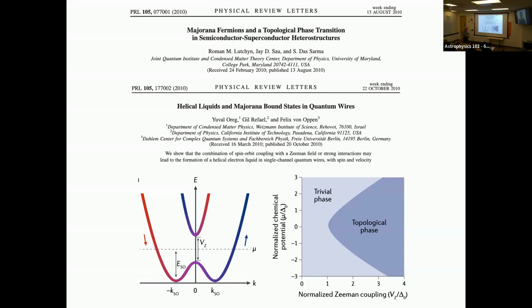What happens when the Zeeman energy exceeds the superconducting gap is, rather than destroying superconductivity, a new superconducting phase appears. With sufficient spin-orbit coupling, that superconducting phase will have this character that it's as if it inverted the gap without destroying superconductivity, and the endpoints will be these Majorana states, which really constitute a single zero energy state for an electron that can live with that state.